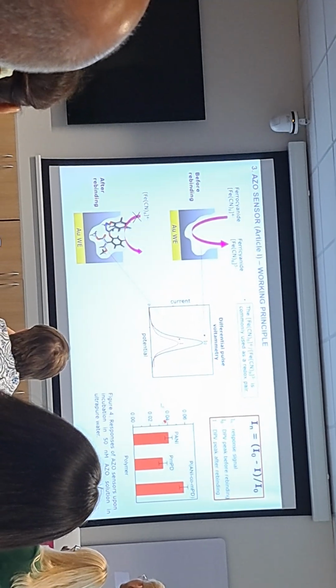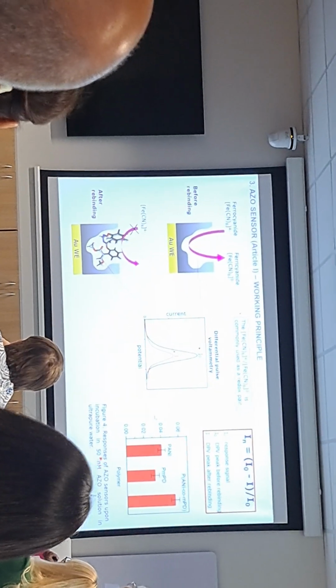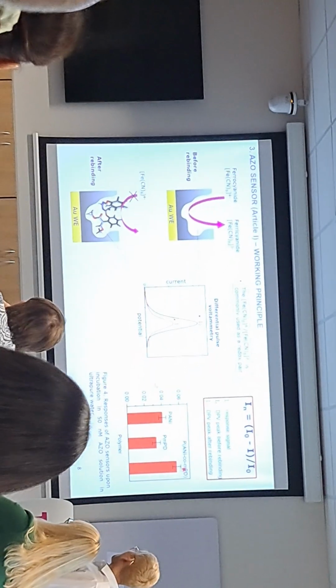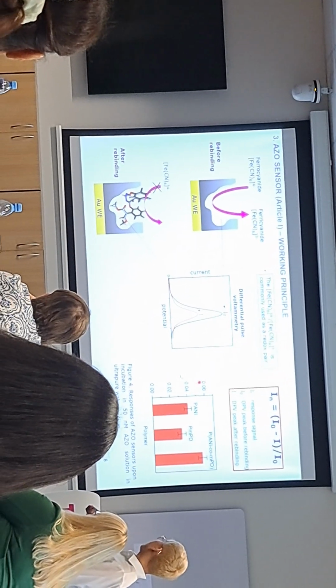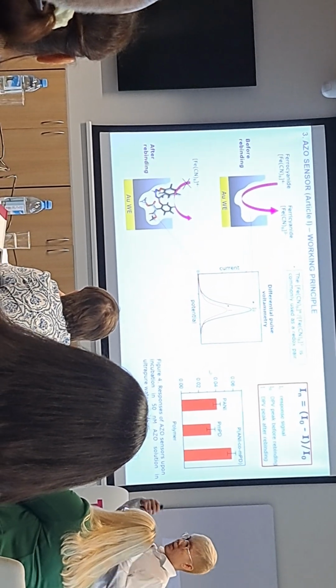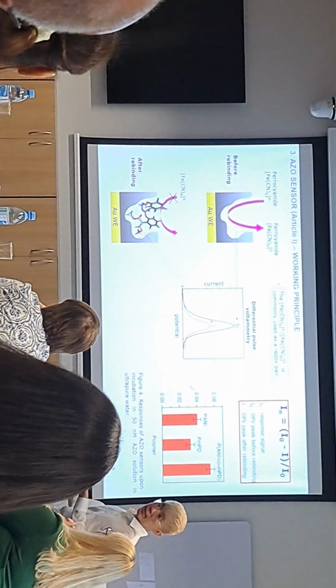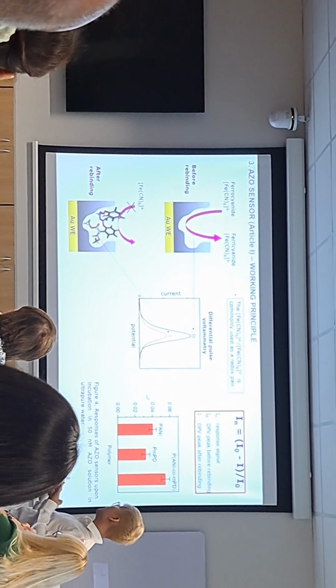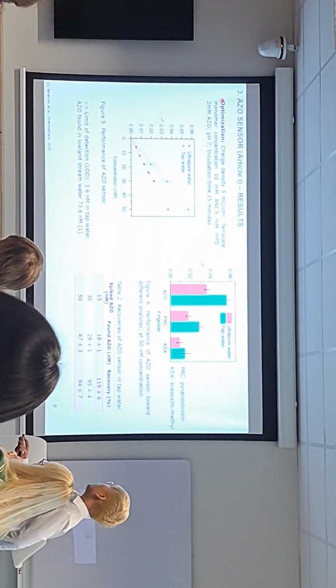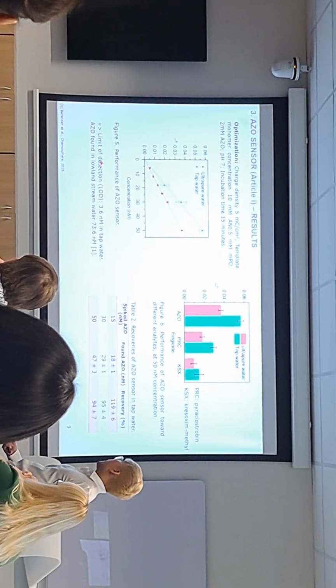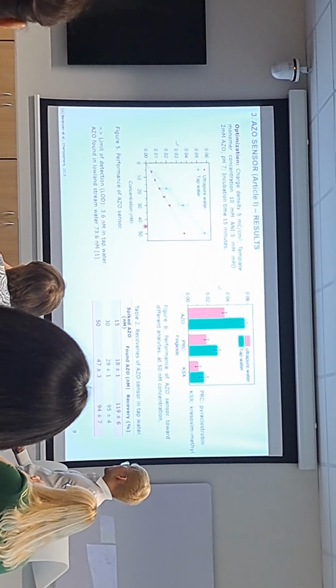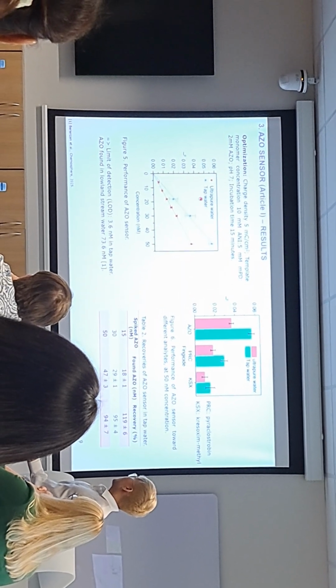And I rebind all of them toward the same concentrations with the same time, and the sensor with the copolymer gives the higher response. It means that my hypothesis about using 2 different monomers is the correct thing to do. And after some stage of optimizations, I refine my sensor with low concentrations in both tap water